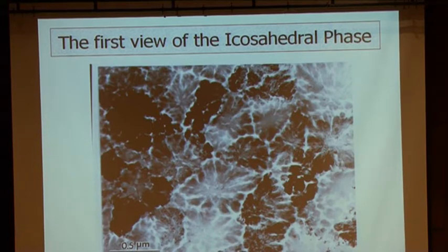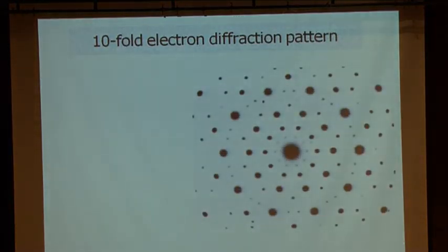This can mean one of two things. Number one, it can mean that the area there is very thick so that the electrons cannot go through. This is obviously not pertinent here because the other area nearby is very thin. Or it can mean that that crystal diffracts heavily. So most of the intensity goes for diffraction. And I said, whoa, that's quite interesting. Let's see what the diffraction pattern looks like. And it looked like that.